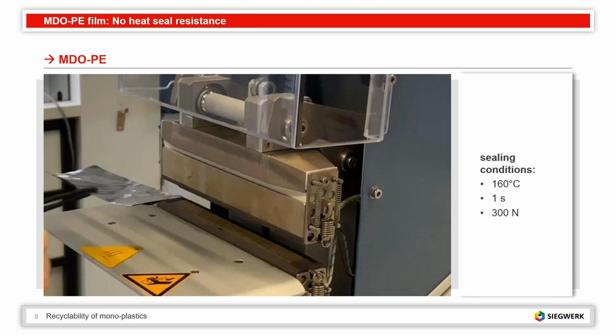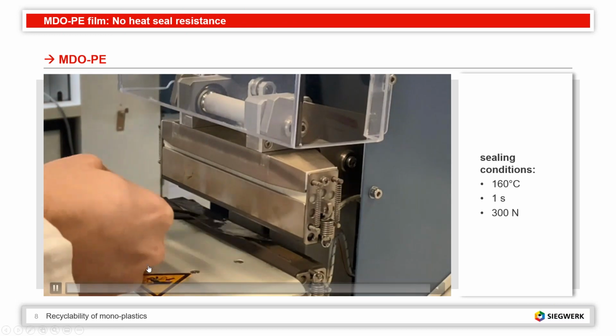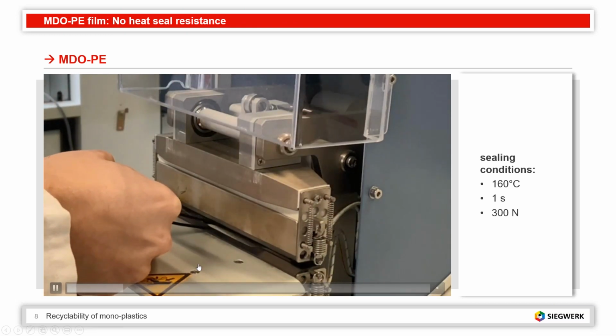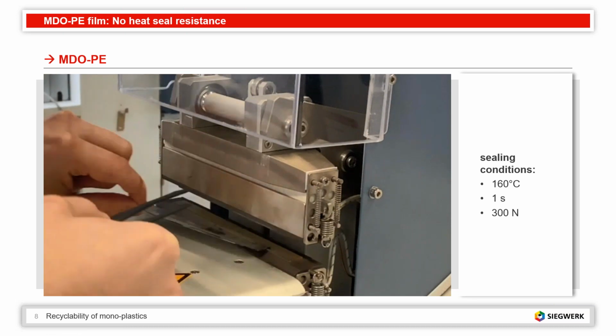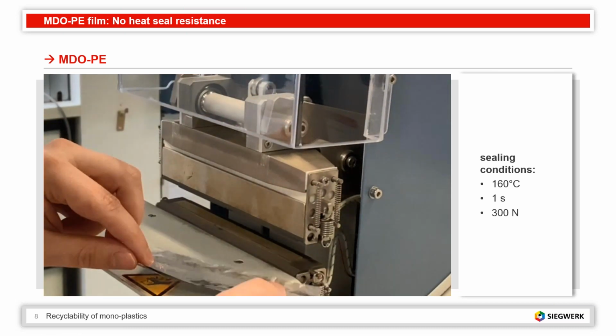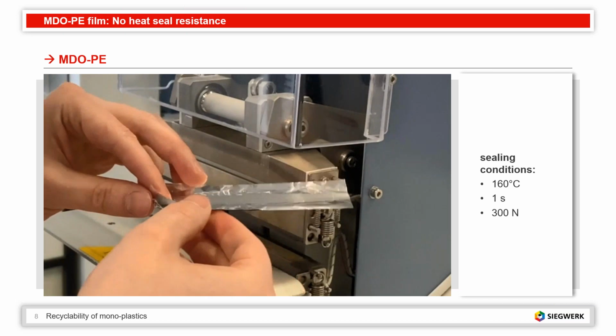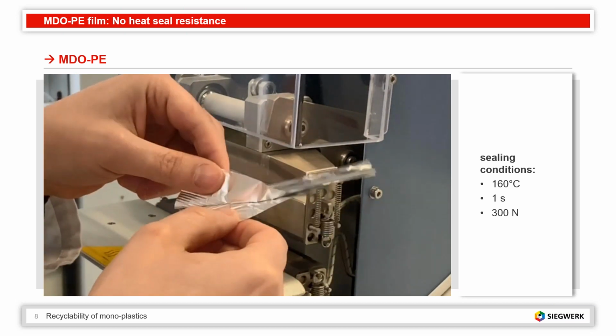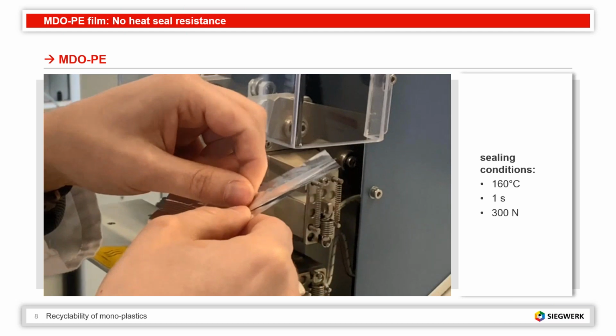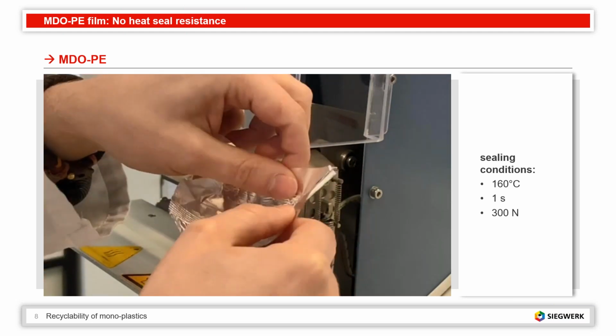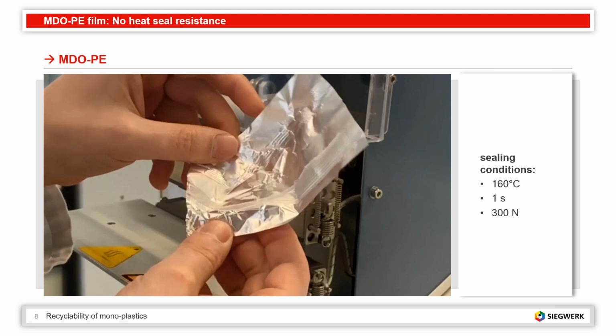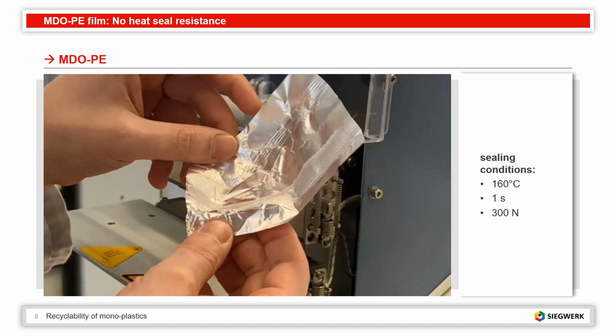However, when you try this with MDO-PE, one of these new MDO-PE films, and this is exactly the same procedure. So the film is between two aluminum layers. Now he takes it out and he tries to open it. And you will see that he's not able, or almost not able, to get those aluminum film layers apart, because the MDO-PE film has basically turned into an adhesive, heat-sensitive adhesive. So no way that you could seal that in any way.